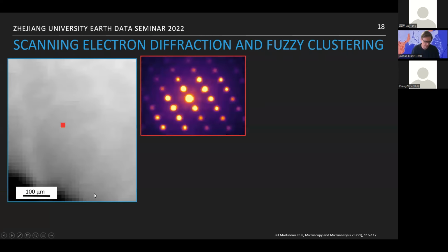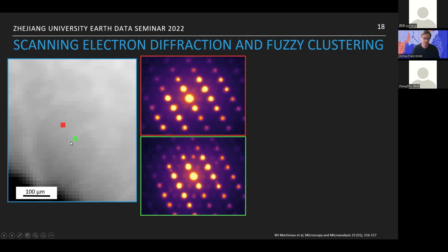So using that technique, we're now able to get these virtual bright field images. If I sample a point anywhere in this data, you can get a diffraction pattern that corresponds to that pixel location. Here we have something that looks largely like tetrataenite. Here we have something that I know from experience is similar to our matrix phase. What you should notice in these two figures is that the diffraction patterns are incredibly similar. The largest feature that's different is this bright little point out here, which for an FCC material is a forbidden reflection. And this gave us a bit of complication.